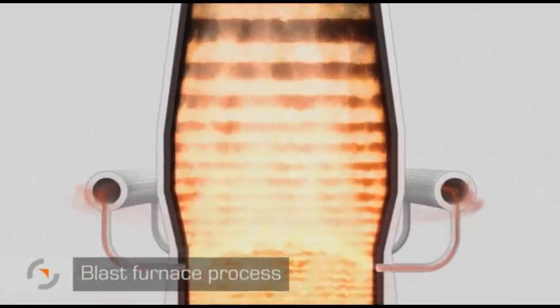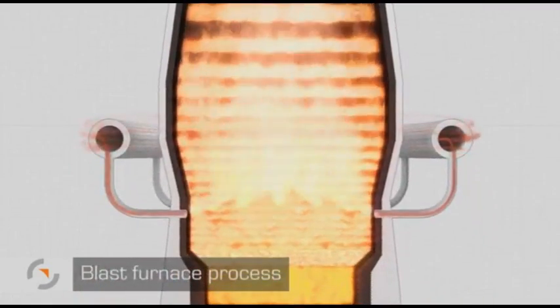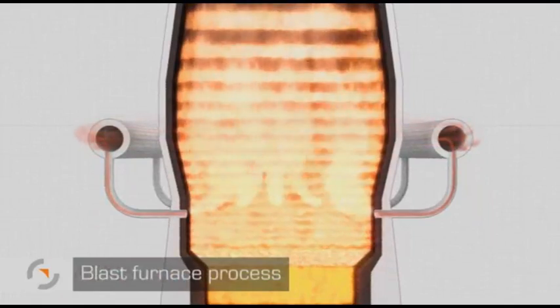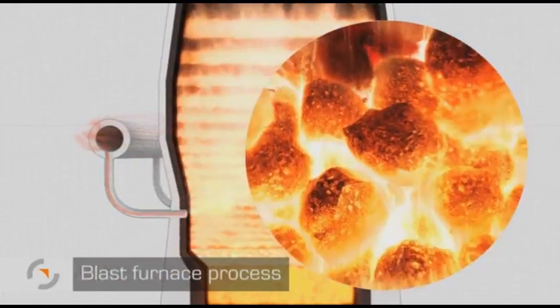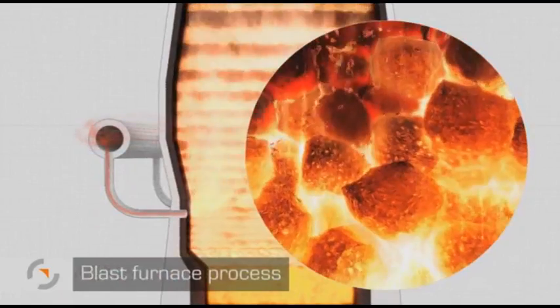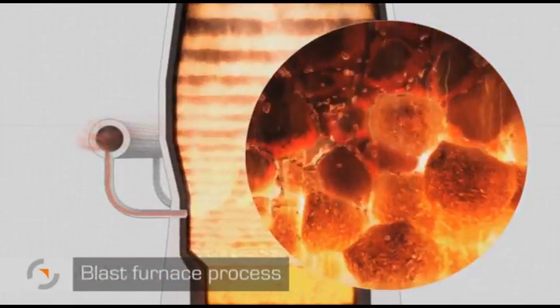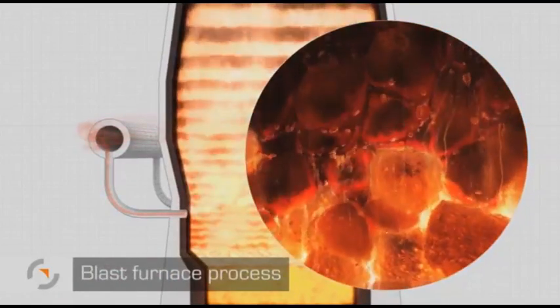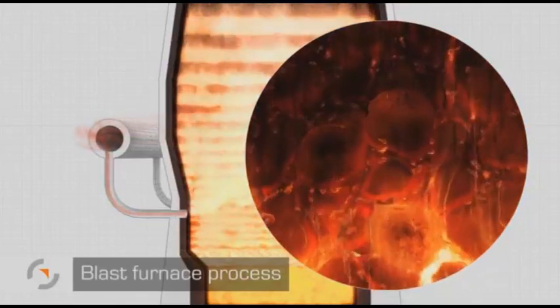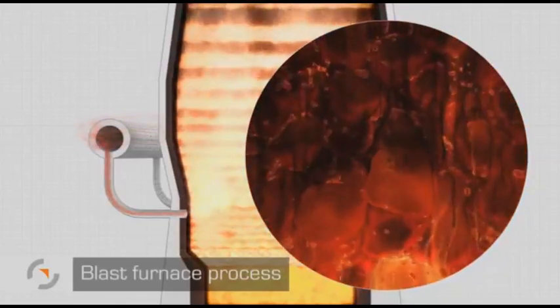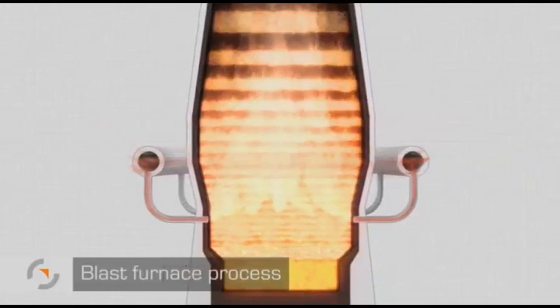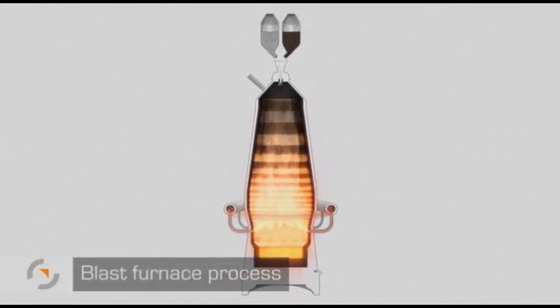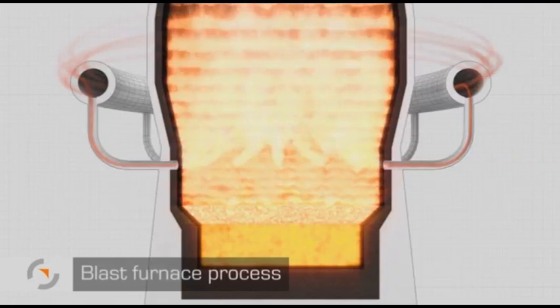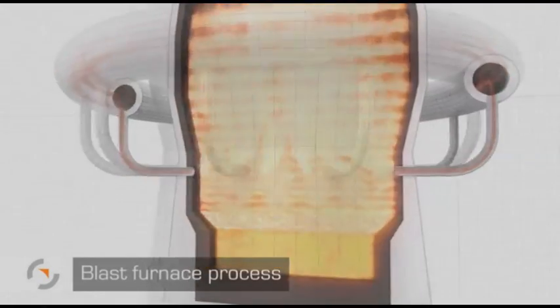Process gas is generated when air, preheated to approximately 1,200 degrees Celsius, is blown into the furnace. The oxygen in the air burns with the coke, generating process gas with a temperature of about 2,000 degrees Celsius. It removes oxygen from the iron oxide and the heat melts the iron. The whole process takes 8 hours, and the resulting liquid iron and slag collect in the lower part of the furnace.